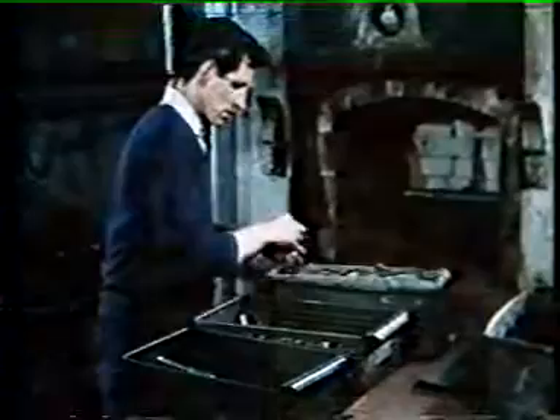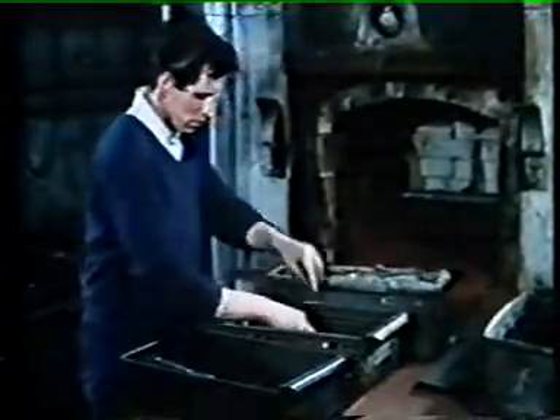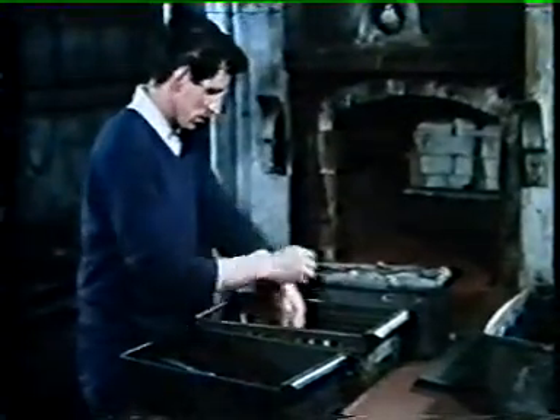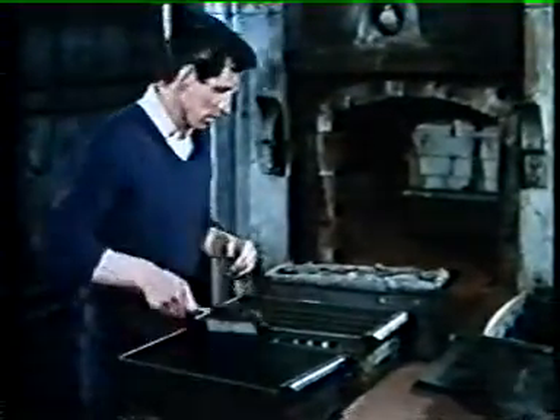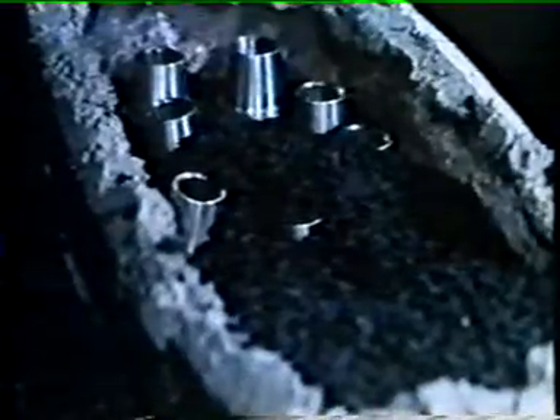The chuck sleeves are then quenched in oil. The tank can be clearly seen in this older type of apparatus, and the steel is hardened at the surface only. The process is known as case hardening, and when an ammonia-containing carbon-rich atmosphere is employed, the method is known as carbonitriding. Another method of case hardening is to pack the components among carbon granules before heating in the furnace. This is known as pack hardening. Yet another method is by immersion in a cyanide salt bath.